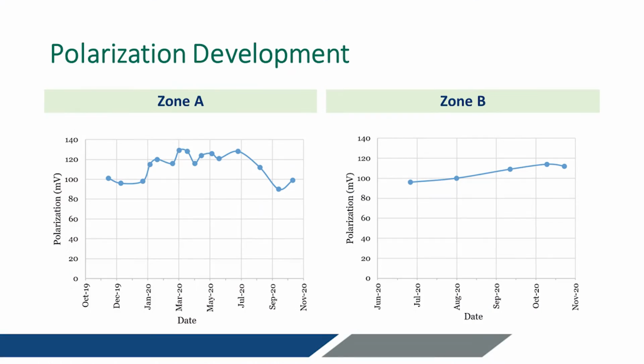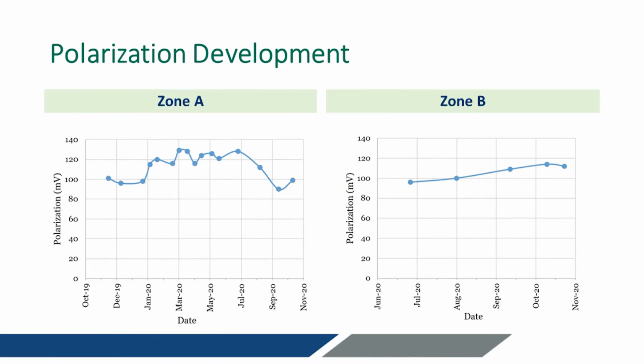Really what we want to see is that the steel is being properly polarized to protect. The anodes are properly polarizing the steel, and usually we want to see about 100 millivolts of polarization. And so over the course of the anode install, we're measuring how much polarization we're getting, and we're seeing that we're easily getting 100 millivolts, a slight drop. Maybe it got cold in September, and so we weren't getting enough, but 90 is very sufficient.